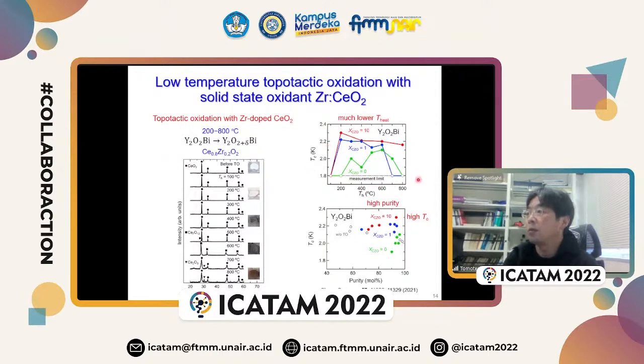In the previous method, we used a 1000 degrees sintering temperature, but by using this solid state oxidant, we can obtain the superconducting Y2O2Bi from above 200 degrees C to 800 degrees C. And by using this method, we can obtain a high purity superconducting compound like this.